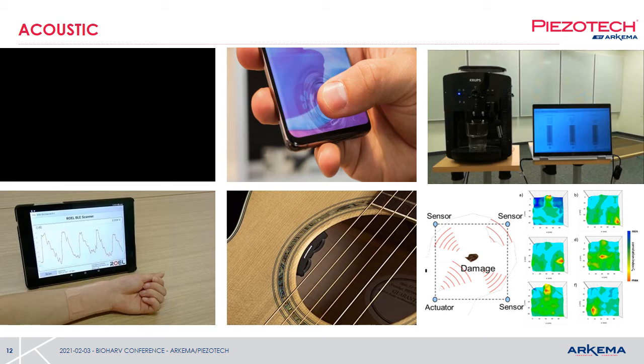Piezo polymers also make very unique microphones, especially for guitars, because they have a very, very flat response over a large range of frequencies. It means that if you play a note at 500 Hertz and another one at 15 kilohertz, you will have the same response from the piezoelectric sensor, so you will have a very good sound detection.